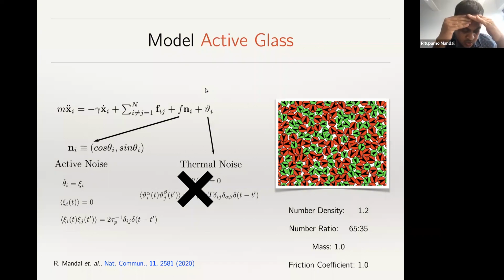Okay, so the interaction energy scale is also different, but if you forget about the scale and look at the diameter, you will see that A has a bigger diameter and B has a smaller diameter. So you can think of this as a mixture of A where you have inserted some B particles, 35% of it, to make the original mixture eutectic. So it doesn't try to go to a crystal easily. That's why you have added these defects of B particles, and people have tried different ratios, and I think they came up with this ratio where it works very well, that it doesn't tend to crystallize and remains disordered for any typical time. Fair.